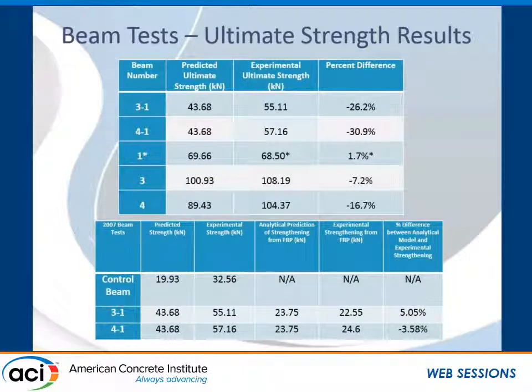Let me note that the two beams from the 2007 tests appeared to have significantly greater experimental strengths than the theoretical prediction would give, but when we took a little closer look at the data, the beams compared comparably to a control beam from 2007 that was not strengthened with FRP. So that control beam also tested much higher than we expected.